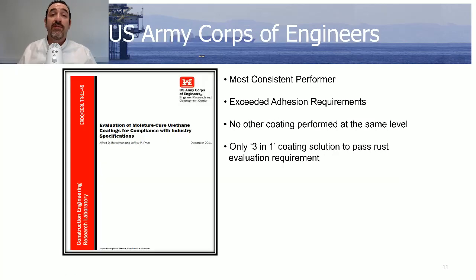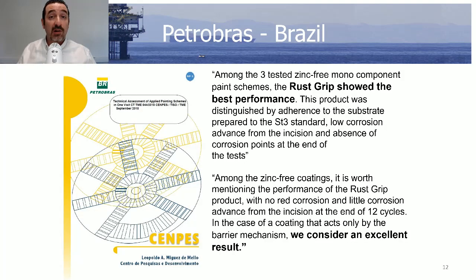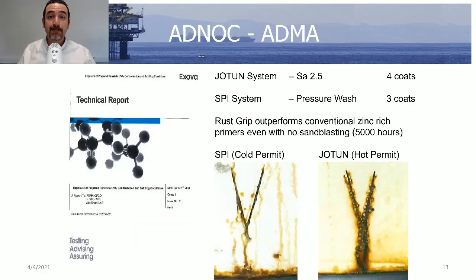The U.S. Army Corps of Engineers has tested a variety of moisture-cure urethanes, and Rust Grip was found to be the most consistent performer. Our client Petrobras did offshore ISO 12944 aggressive testing, and in their words, Rust Grip showed the best performance. We consider this an excellent result after 12 cycles.